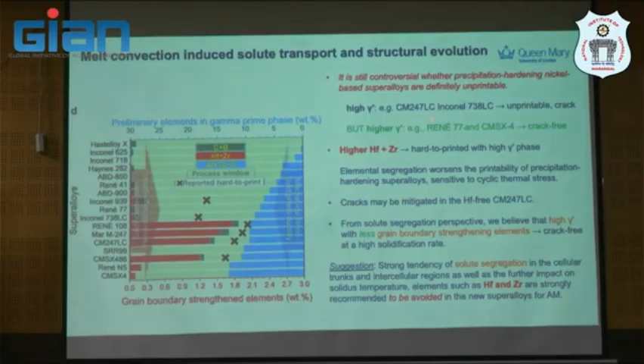So high gamma prime alloys like CM247 or Inconel 738 LC are considered unprintable with cracks, but even higher ones like René 77 are crack free based on the literature.